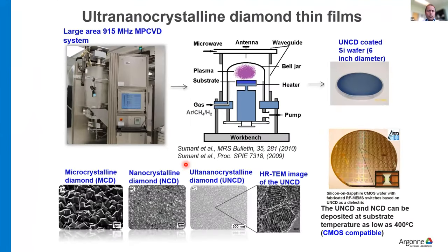So this is the 915 megahertz large area system that we have here at the Center for Nanoscale Materials, which is a user facility. Using this process, we can grow different flavors of diamond, typically ranging in grain size from microcrystalline diamond, with a few microns, to ultra nanocrystalline diamond, where the grain size is just 2 to 5 nanometers, which is shown here in the TEM.